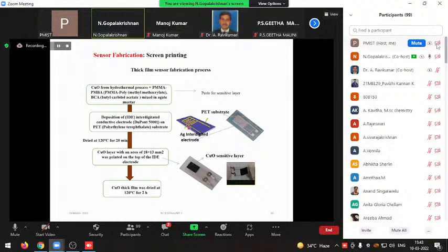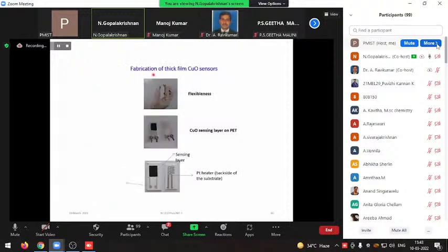So what I want to tell you is that we made the IDE structure on the PET substrate, and we made this copper oxide nanofilm, a nano powder thin film. Then we measured all the parameters for different gases: ethanol, methanol, acetone, or ammonia. We measured gas sensing efficiency and compared it with conventional gas sensing. Again, we showed that the sensing efficiency in this case is higher than in the previous cases.